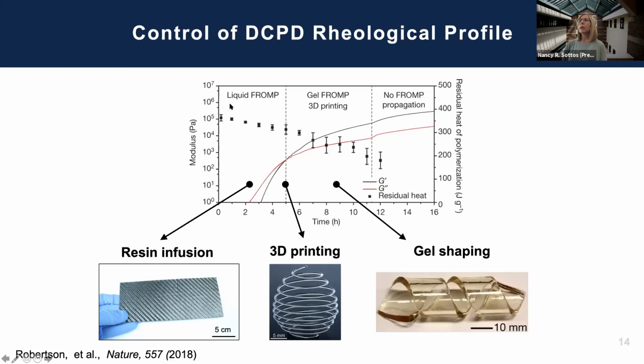And so by tuning the gel point with the amount of inhibitors, we have three different regimes here. Two are useful, but one is important to realize where it is. The first is what we call the liquid FROMP, or frontal ring opening metathesis polymerization. That means we're going to polymerize from the liquid, like in the test tube and the casting cell that I showed before. And this is very useful for resin infusion of composites.